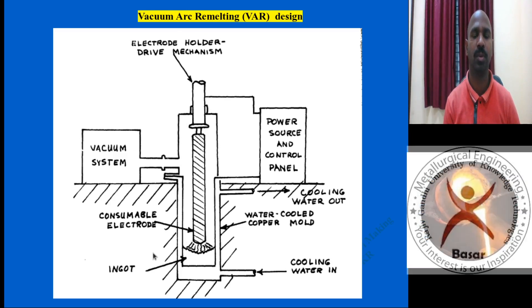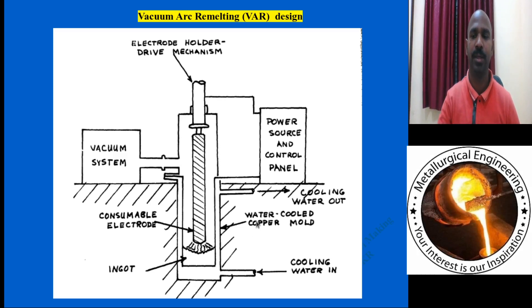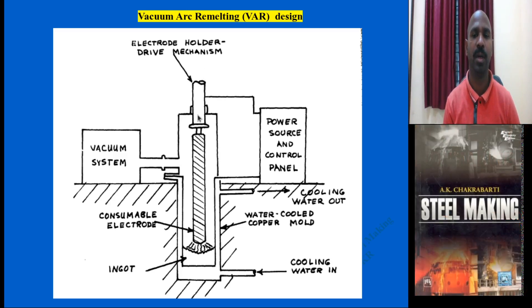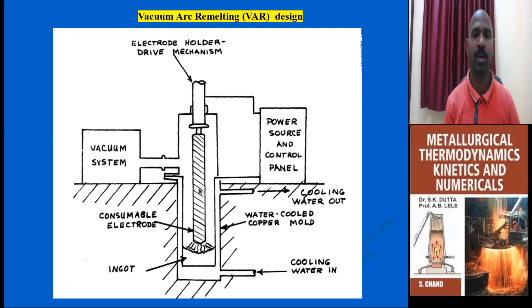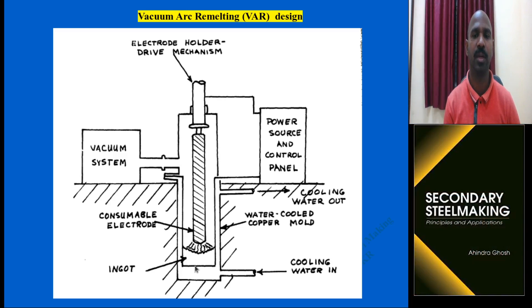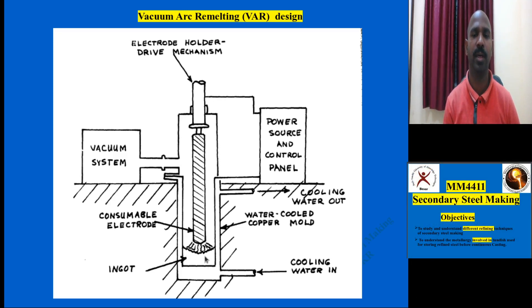The upper part is above ground, the lower part is below ground. The pot is a hollow copper mold continuously water-cooled with water inlet and water outlet. The fixed dummy electrode is welded to the consumable electrode which is going to be remelted and refined. An arc is generated, the electrode melts, and after solidification this forms the ingot — a round ingot of mold shape.